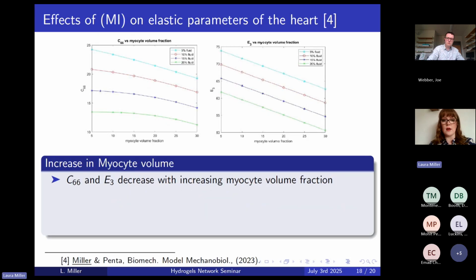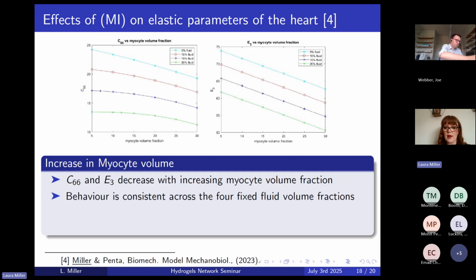I've also presented here a slightly different analysis. This time I'm looking at C66, which is just one of my other shears, and my E3, which is my other Young's modulus. You'll see here that I have different lines, and each of these coloured lines represents a perfusion level of the tissue. So I've got about 5% through to 20% perfusion, which is the vessel volumes. And I've this time carried out my analysis in terms of increase in myocyte volume fraction, to replicate the swelling of the myocytes in the border zone to try to again improve the compliance of the heart muscle itself. Both of them, as we can see, are decreasing with the increasing myocyte volume, and the behaviour is consistent across the 4 fixed fluid volume fractions.